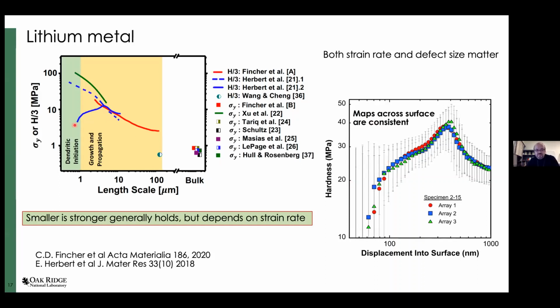So this is a very interesting mechanism, because what happens is if your defect is very, very small, lithium can relieve stress by diffusion. Since the distances are very small, it has just enough space to reduce the stress buildup simply by diffusion. If your length scale is large enough, it can start relieving the stress by dislocation motion. But if there is a defect of just the right size in between those regimes, it will build up stress to very high levels. So this is what can be called a danger zone. So this is quite a peculiar behavior of lithium.